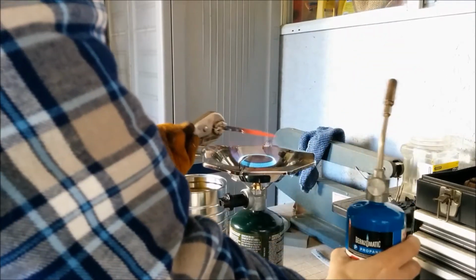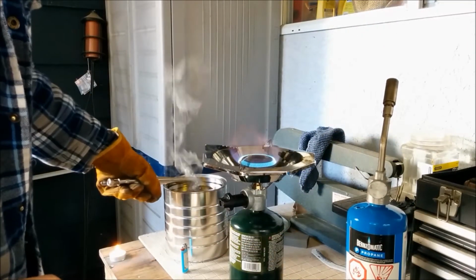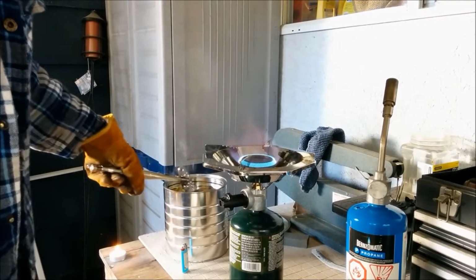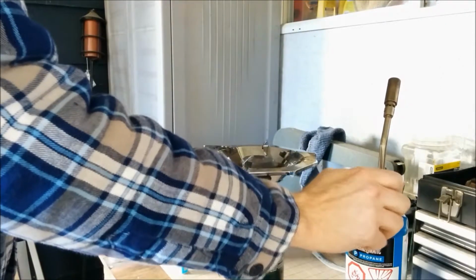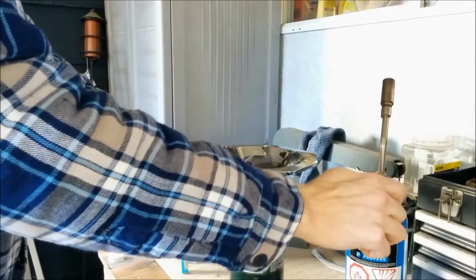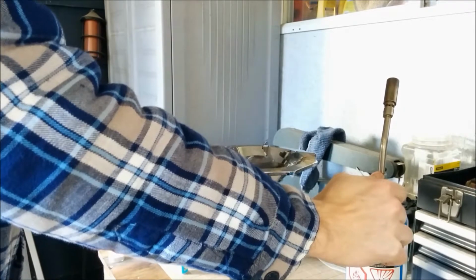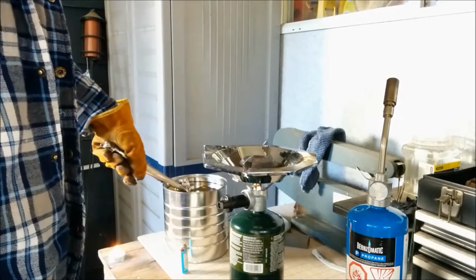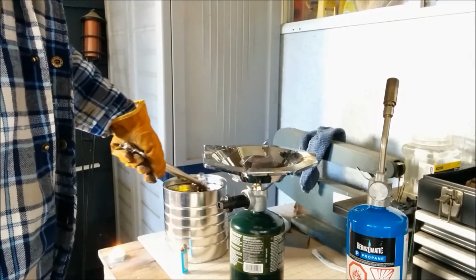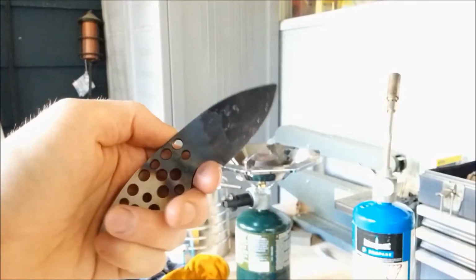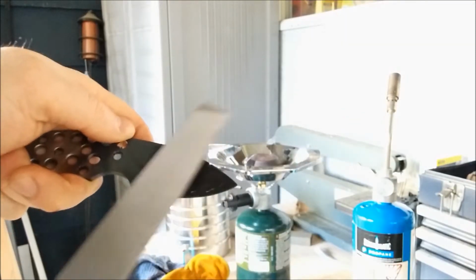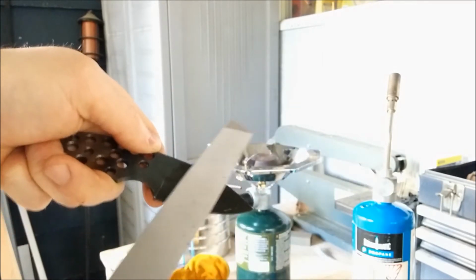And when you go into the quench oil, you want to go back and forth. You don't want to do figure of eights, which people who heat treat other things have been taught. That can actually warp your blade, so it's best to go in a back and forth motion to cool the blade down as easily as possible. Here I'm doing a file test, and the file is skating across the surface, which means I did get hard.